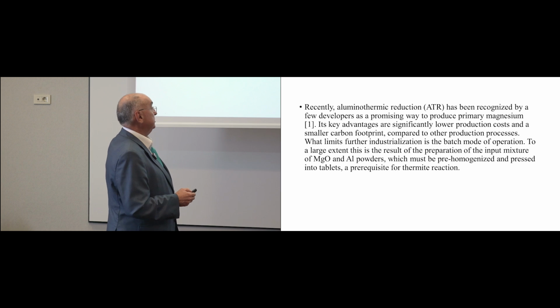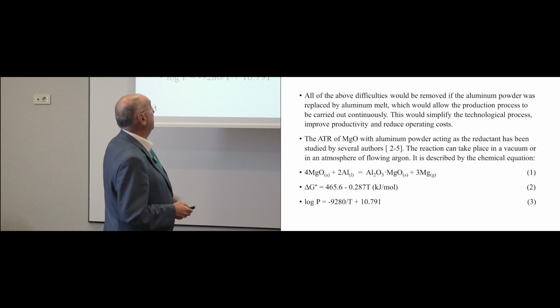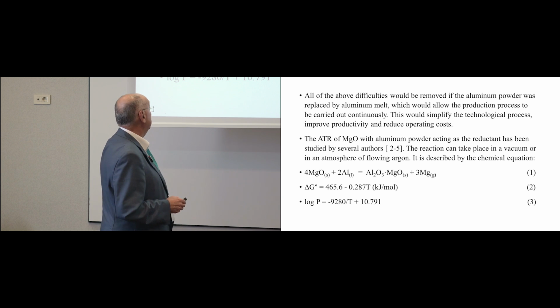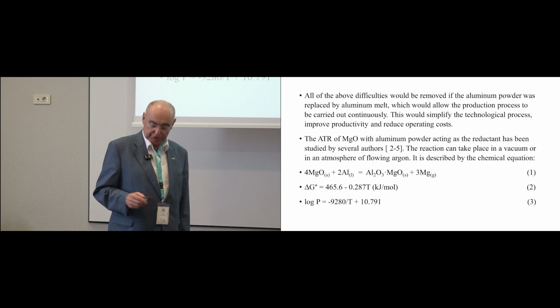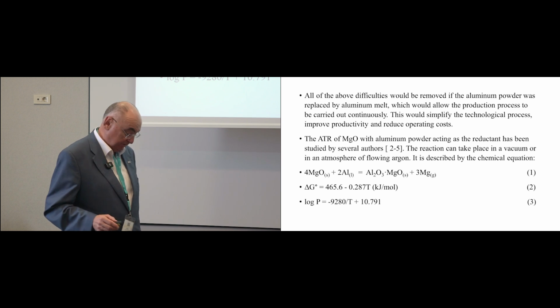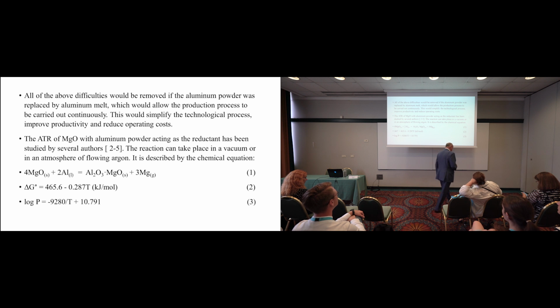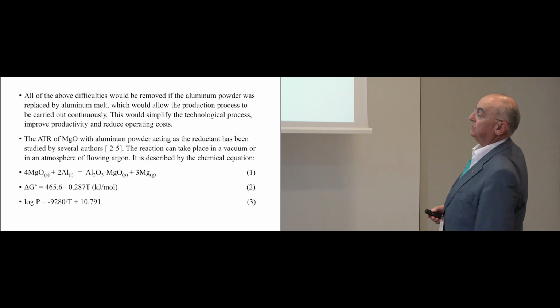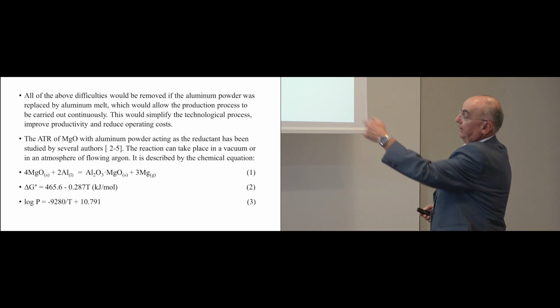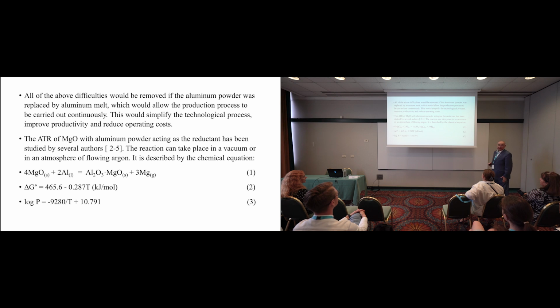So this was the main reason why we tried to, I will not go into details because time is very short. We found in literature and during some conversations that the aluminothermic reduction of magnesium oxide could be the cheapest way. We know that some companies in the United States are making primary magnesium in this way. In principle, it's a very simple reaction: you take magnesium oxide and aluminum as reductant, and then you get spinel, this complex oxide, and primary magnesium.